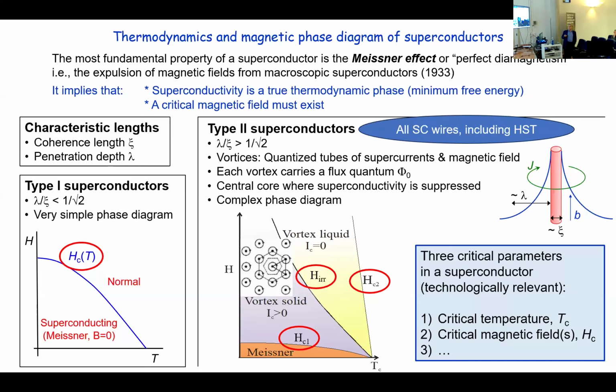In these materials, you have a much more complex phase diagram with an HC1 critical field, an upper critical field HC2, and an irreversibility line that separates two phases that contain vortices. Vortices are very interesting objects that are at the center of the understanding of how superconductors operate for applications. Vortices are quantized tubes of supercurrents with an associated magnetic field. Each vortex carries one flux quantum and has a central core where the superconductivity is suppressed. And that produces a complex phase diagram with several vortex solid and vortex liquid phases. And those are the materials of our interest here.